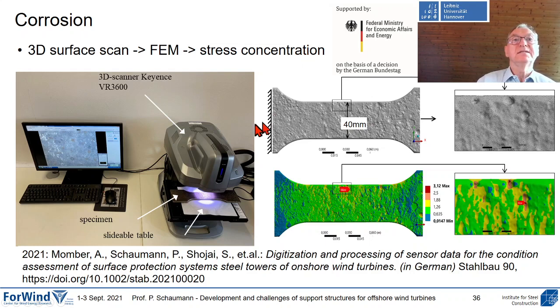And our idea is that we take a scan of our specimen to identify in detail the surface conditions, then transfer the surface conditions into a finite element model, and with this finite element model investigate the stress concentration in our specimen. So you say this is fine for the test specimen in our laboratory. What are we going to do with the foundations on site? So this is very clear, and we developed an idea which you can say we took from our dentists. We produce a replica with a specific kind of material.